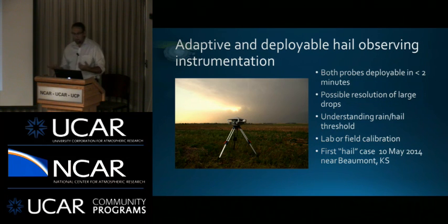The question becomes calibration. So in the lab, I can take a compressed air can, essentially a fancy potato gun, shoot ice stones at this at a known velocity, look at the impact signal, and develop the calibration curve that way, assuming hailstones all fall at their terminal velocity, and work off that to back out a size bin. Or, as what we've actually done, we measured hail at the location of the probe. So now we have a distribution of sizes that the probe likely may have seen.